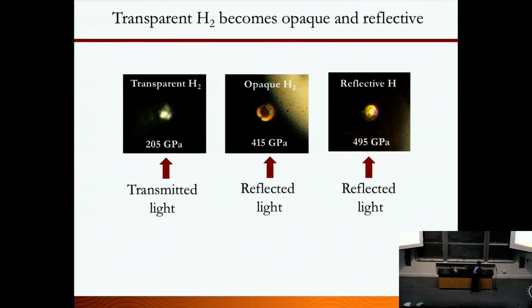Even right here, this image is not that good, but if you look at it on a computer, you can clearly see the boundary of the sample, hydrogen, and then the gasket area. You will not see that otherwise. On the other hand, even if it becomes metal, it's thin enough that it will be transparent, and you will not really see it.